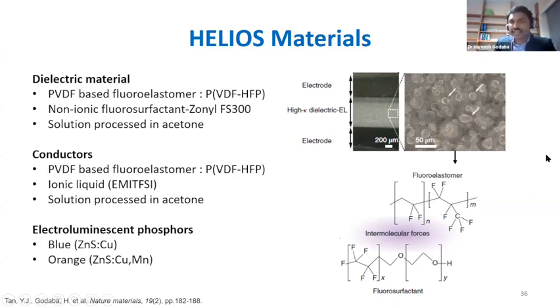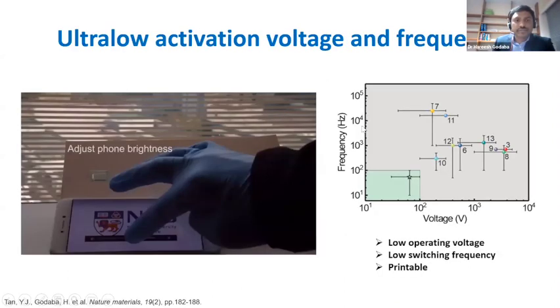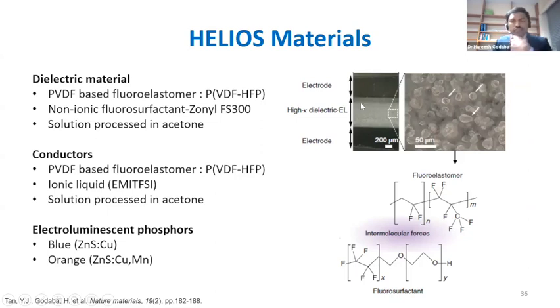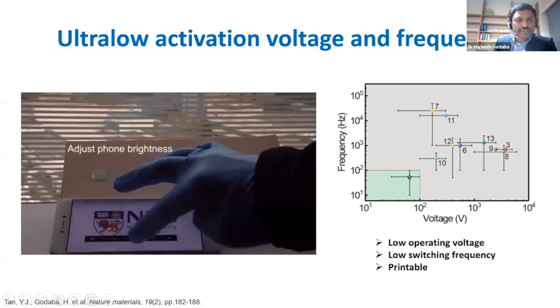And finally, for this intermediate layer, we use electroluminescent phosphors. You can see we have blue, ZnS, zinc sulfide doped with copper, and orange, doped with copper and manganese. And these are, you can see, around 20 micron or smaller semiconductor phosphor particles. So these are embedded into this dielectric material. Now when you apply AC voltage, it will trigger these electroluminescent centers, and it generates light that can emit through this transparent electrode. And here you can see a video of this.